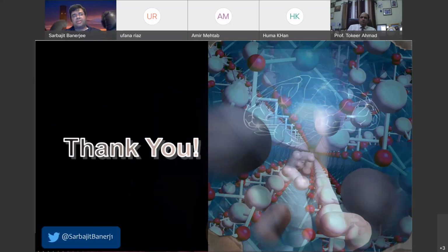A simplistic view is to say, look, vanadium's getting oxidized, or vanadium's getting reduced, or manganese is getting oxidized. But these are crystalline solids with a band structure, and it's not pure metals that are getting oxidized. It's these hybrid states. And so understanding how hybridization affects these states, understanding that you tend to have in all of these compounds some covalency. So, for instance, something extremely interesting that we've been looking at is the lithium-oxygen interactions in these compounds, which for the most part are ionic but have a covalent contribution depending on the nature of the structure. So this is also extremely important.